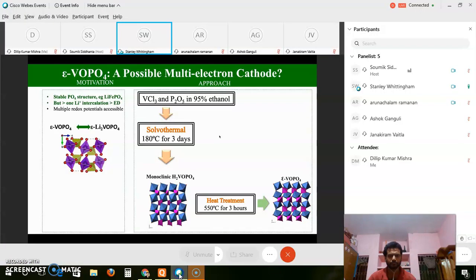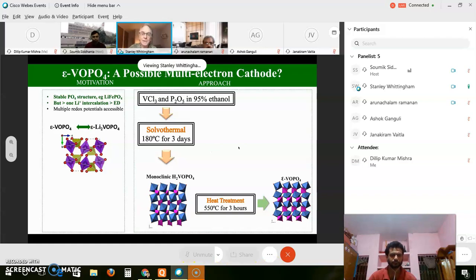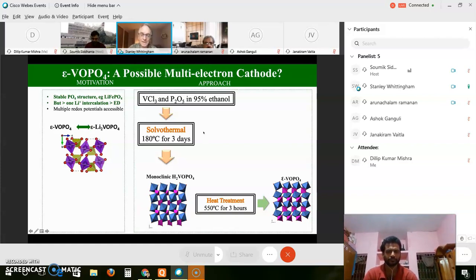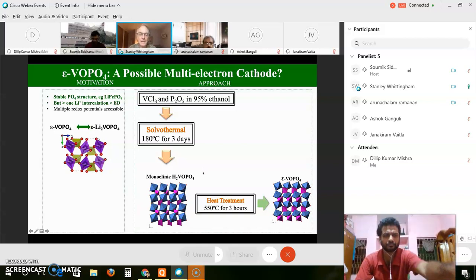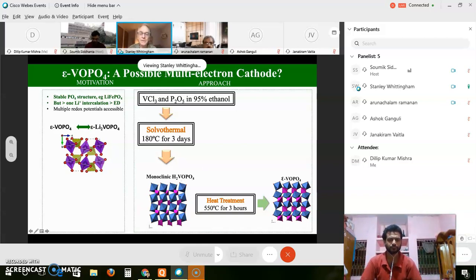Approach to make materials at lower temperatures so we can make metastable materials. So this material, we reacted for 3 days. I think 1 day is enough, but 3 days is a nice weekend. If you do that, then you make the hydrogen analog of this material. A low temperature heat treatment gets rid of the protons, or you can chemically remove these protons or electrochemically at room temperature. So make this nice structure.